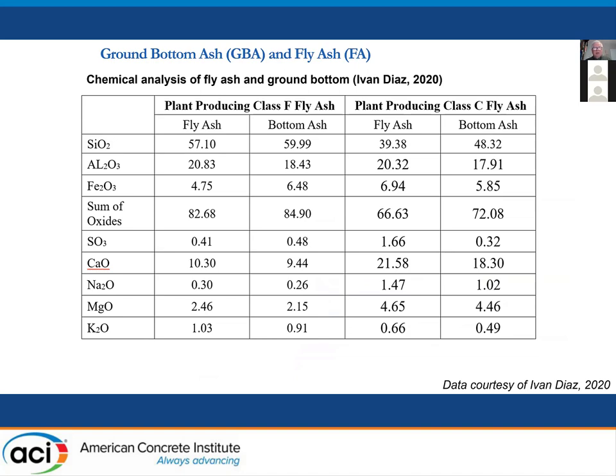Here are some examples from one of Ivan Diaz's papers, showing the difference at a given source. There's an F ash on the left, and the difference in chemical composition between fly ash and bottom ash is almost identical. And the same with the C ash on the right. So chemically, they're pretty much identical. There shouldn't be an issue there.